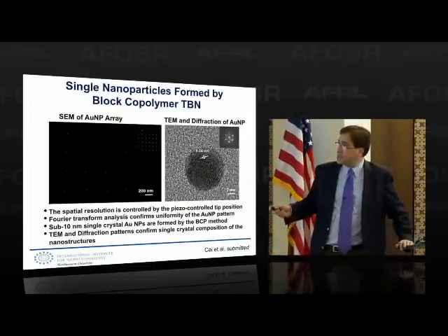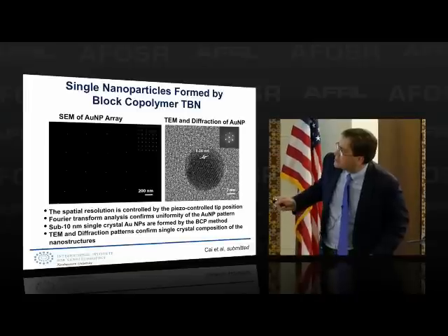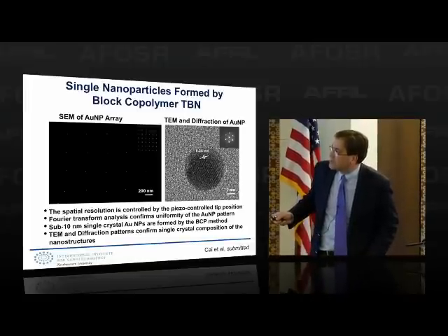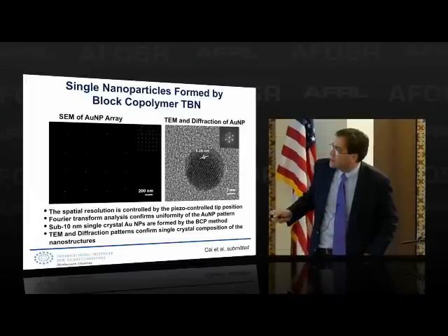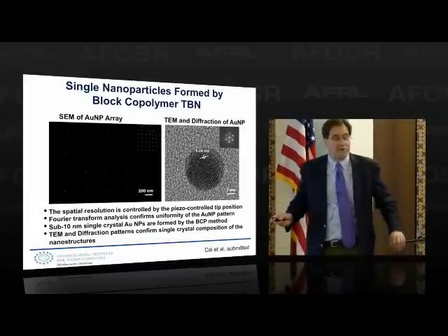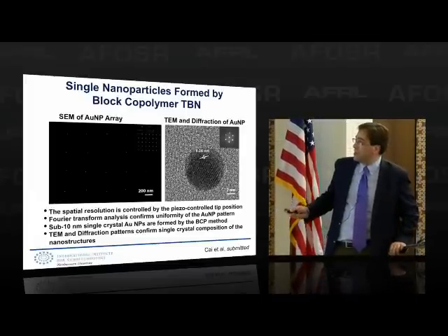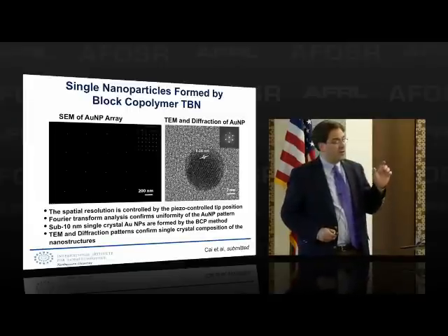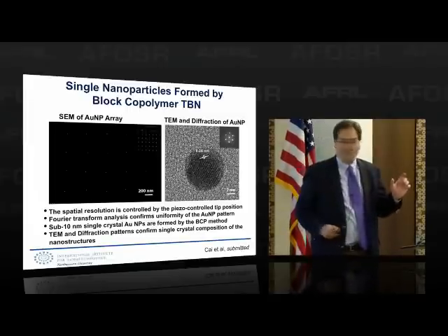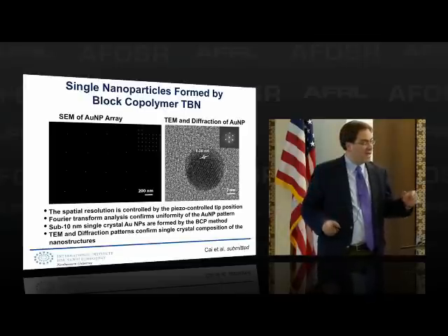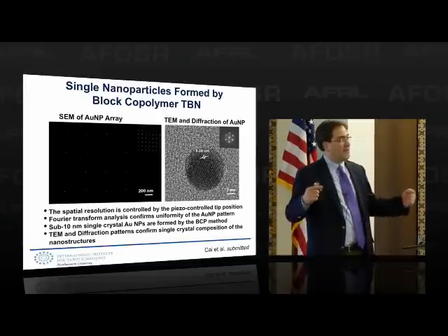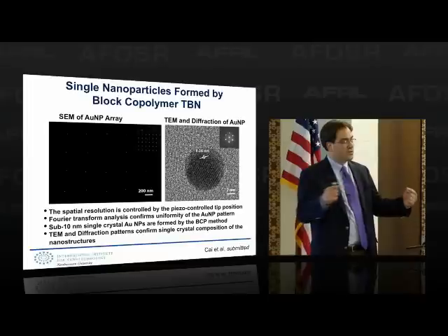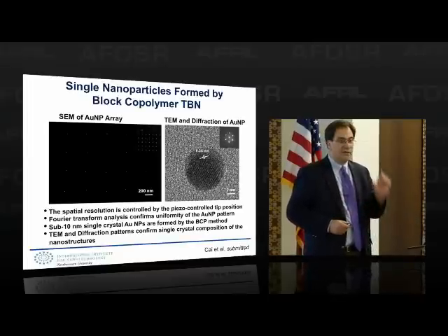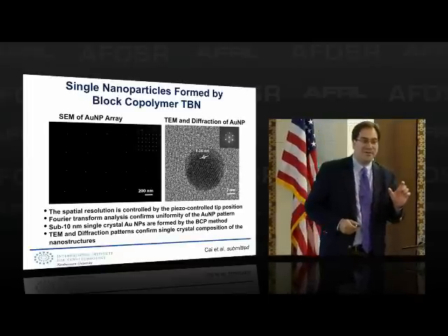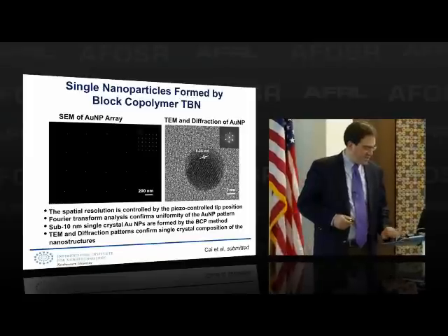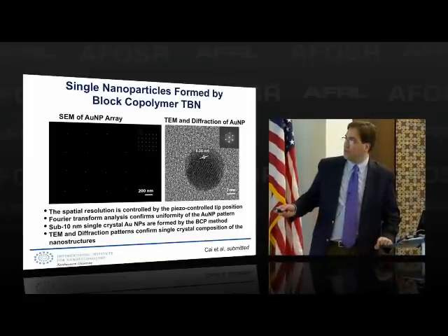And this is then the experiment. I think you can see, at least up here you can see, but each one of these are dots. You can see the dots? Very hard, I think up in the front you can see these, but if I magnify these, you can see they are literally gold single crystals. You see the lattice fringes, they're gorgeous. Every atom in that polymer feature gets reduced and comes together to form a little single crystal nanoparticle. And so in principle, what that means is you have a way to control particle size.